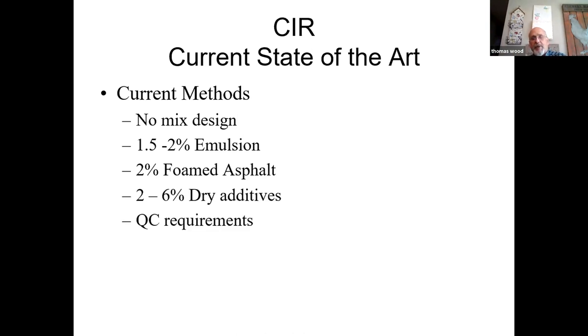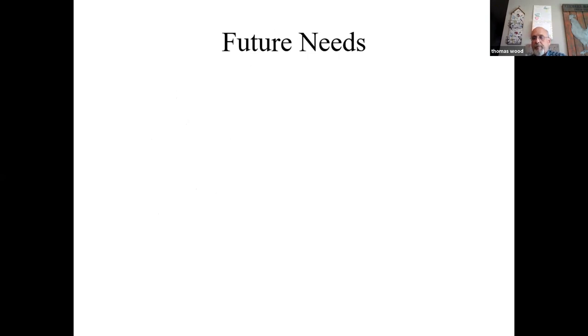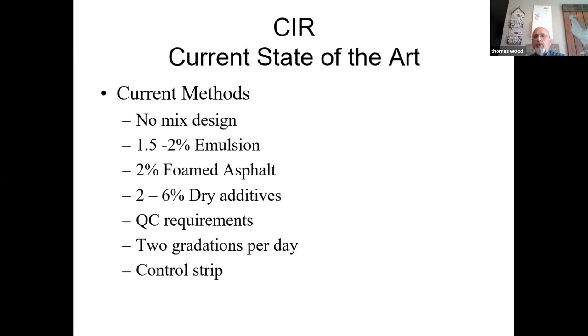Dry additives, 2 to 6%. Need quality control requirements. To me, you need to run at least 2 gradations a day, and you need to construct a control strip for your rolling and compacting effort. And if you see the gradation changing, in the morning it's coarse, and you set up your rolling pattern, then in the afternoon when it gets hot, it becomes finer because the millings are milling finer. You need to reestablish your rolling control strip.